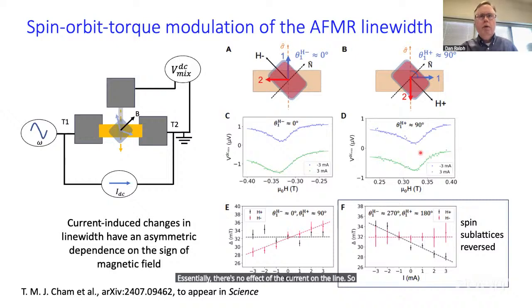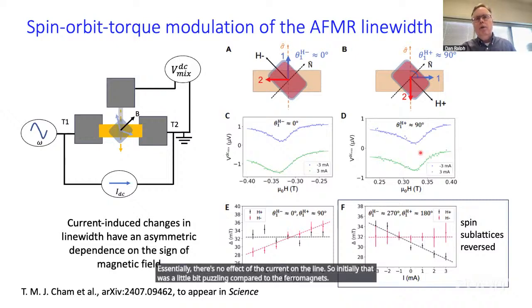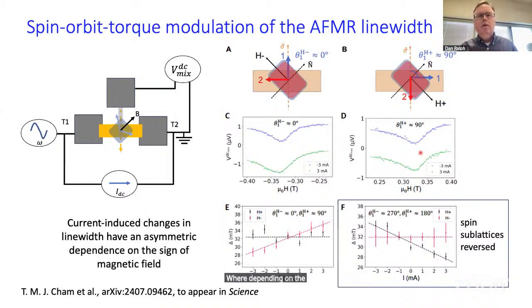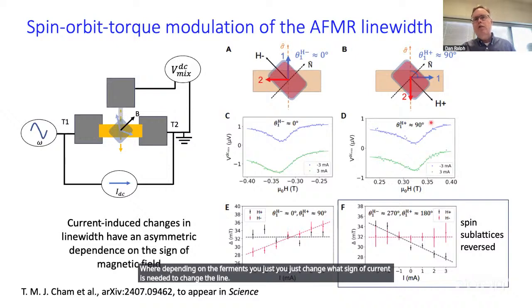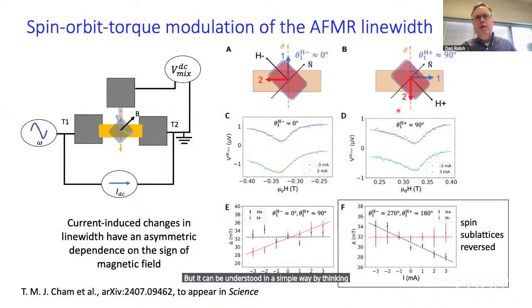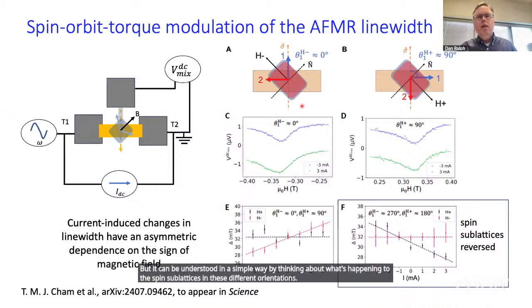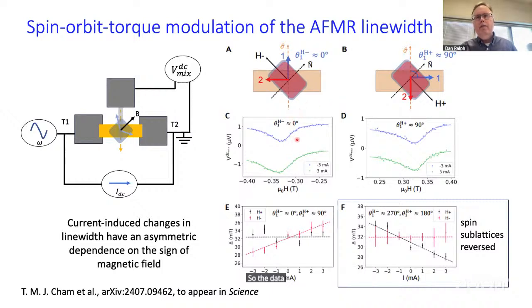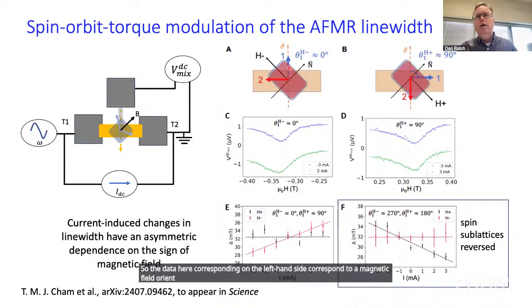So initially that was a little bit puzzling compared to the ferromagnets, where you just change what sign of current is needed to change the line width. But it can be understood in a simple way by thinking about what's happening to the spin sublattices in these different orientations. The data on the left-hand side correspond to a magnetic field oriented such that there's about a 90-degree offset between the two spin sublattices, with one of them oriented perpendicular to the current direction and one of them oriented parallel to the current direction.